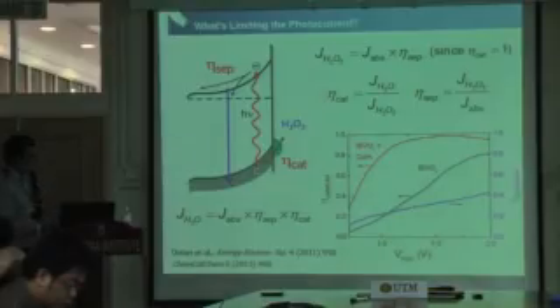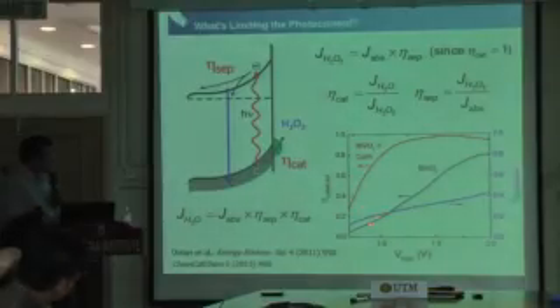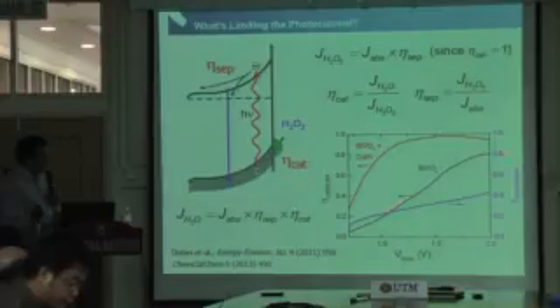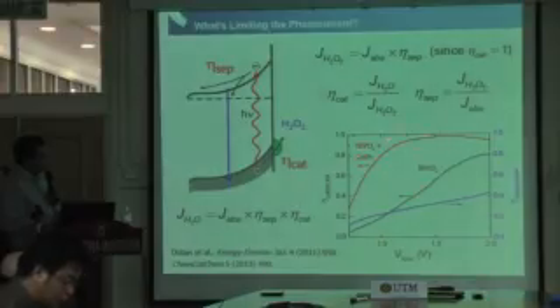So we did that for our bismuth vanadate. The black curve here is the catalytic efficiency of our bismuth vanadate. And as soon as we put on the cobalt phosphate, it improves significantly. It's even already very close to 1 here, or 100%.